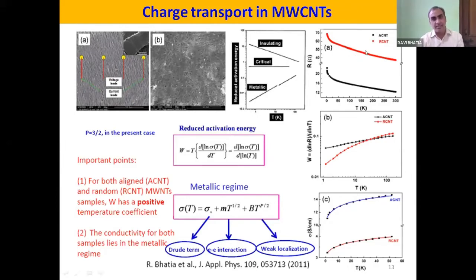The sample under study is showing a metallic behavior, and it follows the equation sigma as a function of T, sigma naught plus m T power half plus B T power p by 2, where the first term is the Drude term, the second term is electron-electron interaction, and the third is weak localization. So the rise in resistance with the lowering temperature is caused by these two terms, that is electron-electron interaction and weak localization. I will briefly explain weak localization.